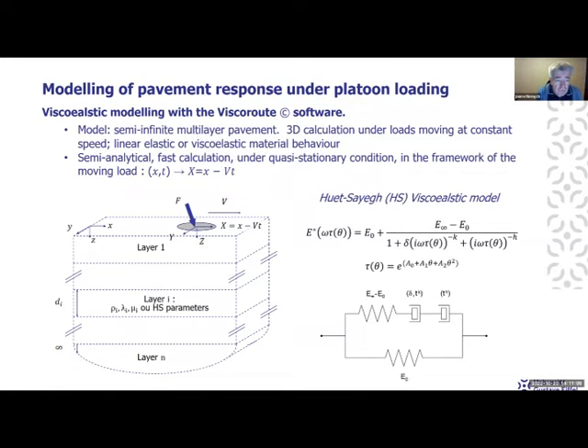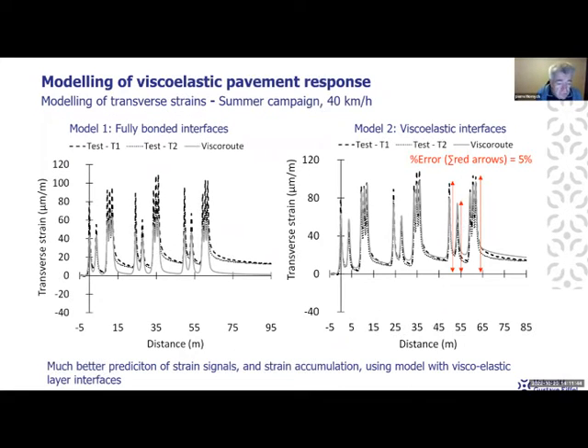And so first we tried to model the viscoelastic response. So we used the software that was developed in our university called ViscoRoute, which is a multi-layer viscoelastic calculation software. So it calculates the response of the pavement in 3D under loads moving at constant speed. And the material layers can be linear elastic or viscoelastic. And for the viscoelastic behavior, we use the Huet-Sayegh model, which is a model which reproduces very well the behavior of asphalt materials. And so we first tried to calibrate the model on the measurements. And we were modeling mainly the transverse strains.